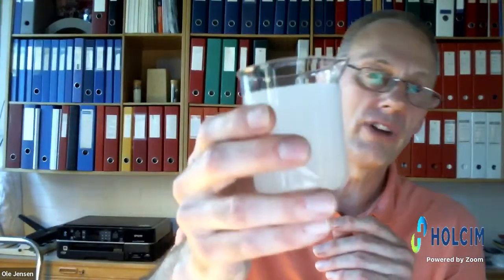And some of the types I show you here also depend on their morphology. For the very fast one I showed you, the individual particles are quite small and they have a broccoli shape, so water very easily gets access to them, and this is why it's so incredibly fast. The polymers you put into concrete, of the type which I have been using and testing, may have particle sizes of 30, 50, 100 micrometer, and when they swell up they will be twice, 2.5 times larger. And these enormous swelling capacities I showed you, 100, 200 times their own weight in water, do not occur so much in concrete because of the ionicity of the pore fluid. So there we will typically talk about absorptions of 20 or 30 times their own weight, 15 times, such like.